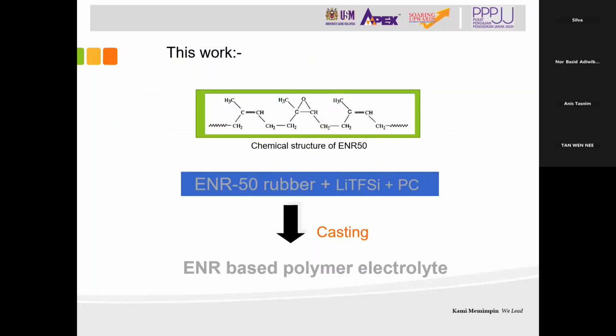ENR50 is commonly used in a variety of applications due to its enhanced properties compared to conventional natural rubber. ENR50 is a modified version of natural rubber where around 50% of the double bonds in the polymer chain are epoxidized. That means oxygen atoms are introduced into the polymer backbone. This modification provides several benefits, particularly improved chemical resistance, flexibility, and compatibility with other materials.